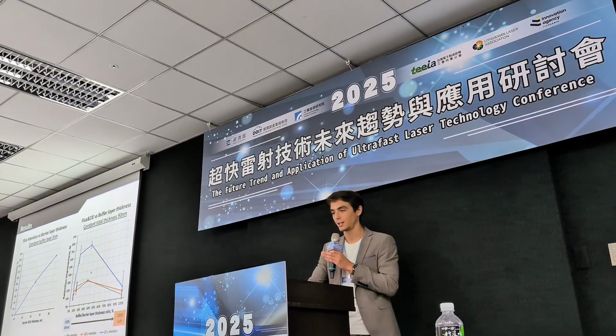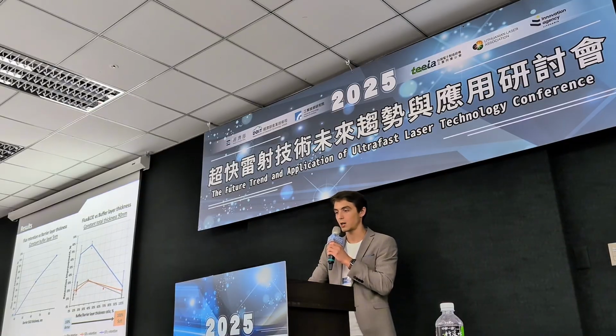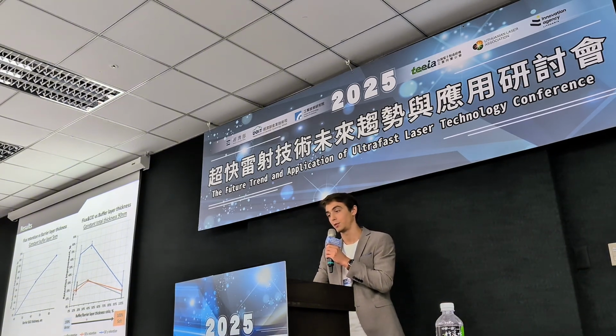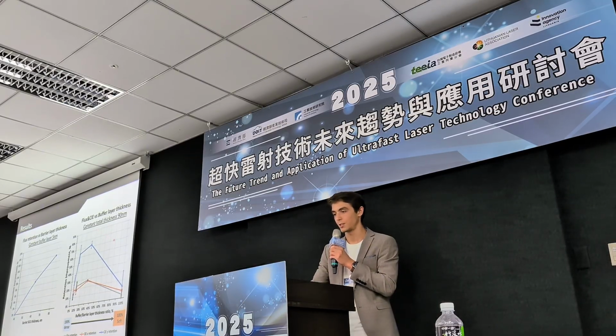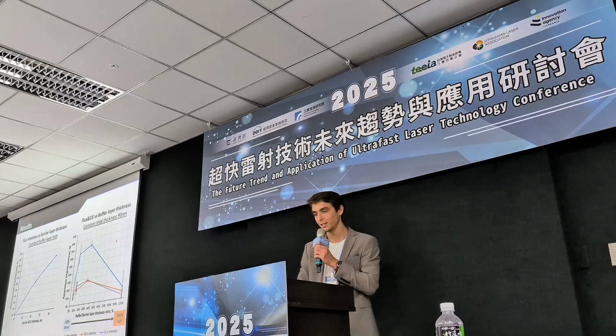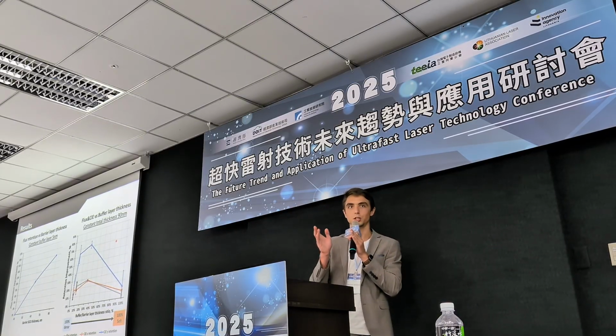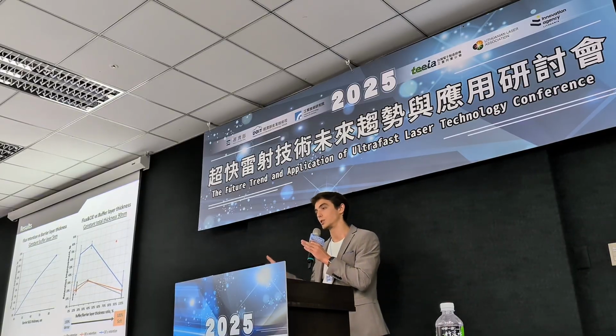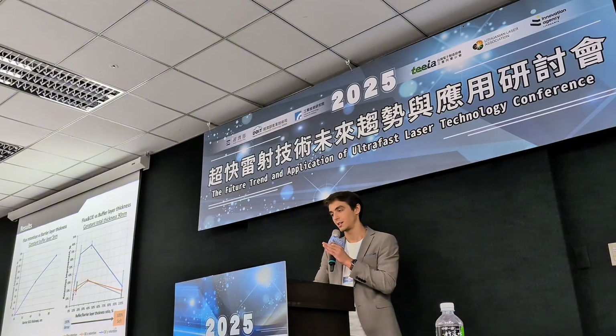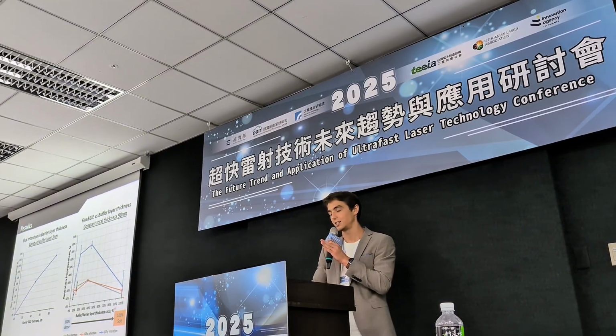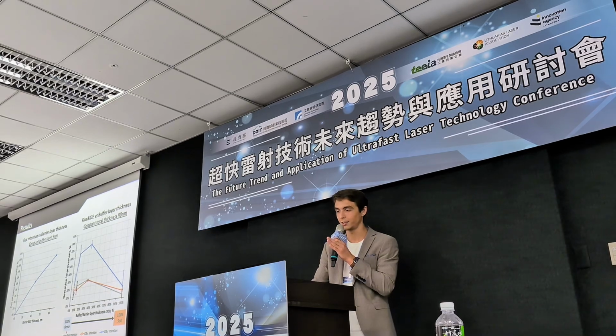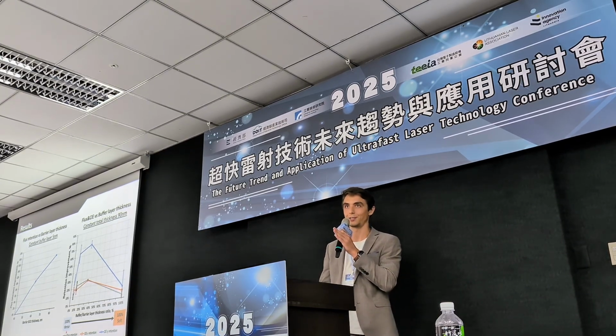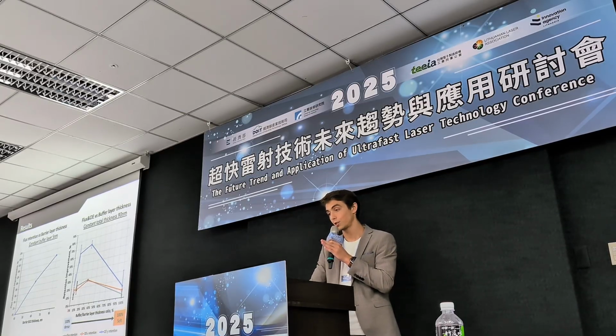From the right side, it shows how optical retention was improved while balancing the ratio between the buffer layer and barrier layer, keeping the total thickness constant. It's a classic balancing task, between process-induced damage of the LED and coating quality. On one side is completely soft silicon dioxide, which doesn't pass the environmental stress test. On the other side is 100% dense silicon dioxide, where the LED was destroyed already after the coating. The good result is somewhere in between the soft layer and the dense layer.